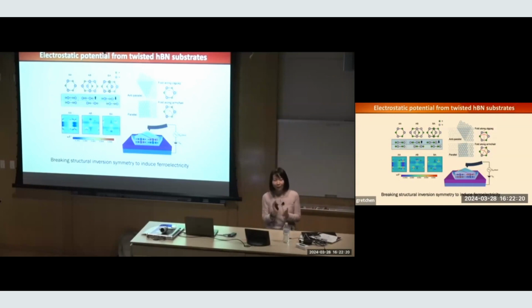I already told you about twisted-hBN. We use it to encapsulate the sample. It's atomically smooth. It's this van der Waals material. You can create an interface that's atomically smooth. And if you sandwich your bilayers between twisted-hBN, the Moiré seems to get more uniform. Everybody gets their twisted-hBN from a group, the best quality twisted-hBN from a group in Japan, right? All the groups pushing for the most advanced physical phenomena get that from them.